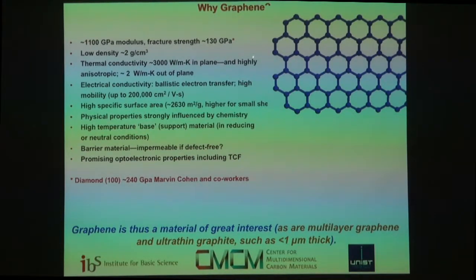So, why are we interested in graphene? I just list out some of the reasons here. It is often said in the popular press that graphene is the strongest material that could exist, so I just want to show you that that isn't true. If we talk about defect-free materials, diamond along the 100 direction will be stronger, all things being equal. So it's often also mistakenly said or discussed that strength is something like a thermodynamic parameter, but it isn't. It's a kinetic parameter.